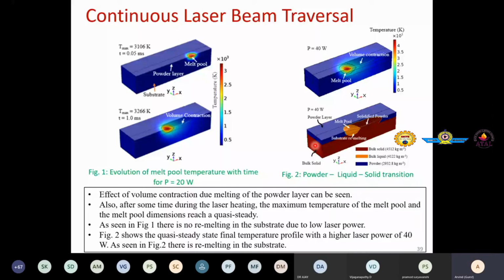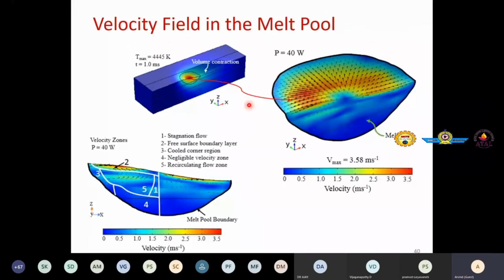More on this fluid flow in the melt pool, you can see it is complex. Here you can see a transverse view. Various kinds of fluid flow are possible, like the regions marked 1 to 5. 1 is stagnation flow, 2 is free surface boundary layer flow, 3 is cooled corner region in the melt pool, 4 is negligible velocity, and 5 is recirculating zone. So you can understand the melt pool flow is not similar to a laser welding melt pool. It is even more complicated than a laser welding melt pool. And the velocity magnitude in the melt pool is quite significant. The maximum velocity in this melt pool was up to 3.5 meter per second, which is quite high in such a small melt pool.